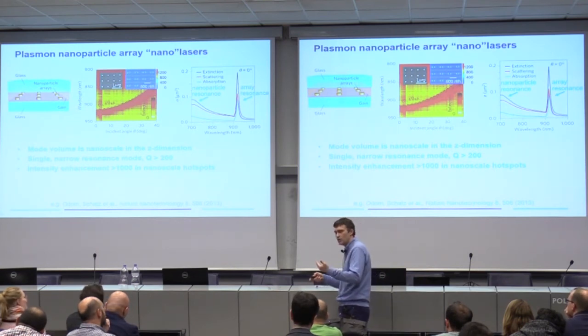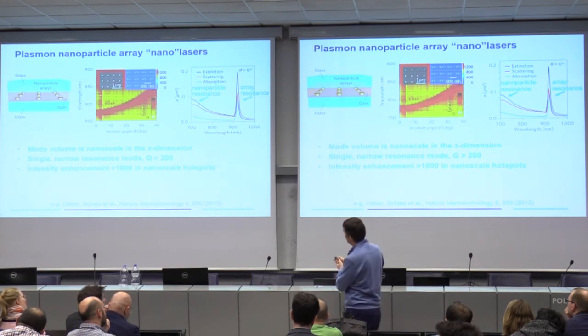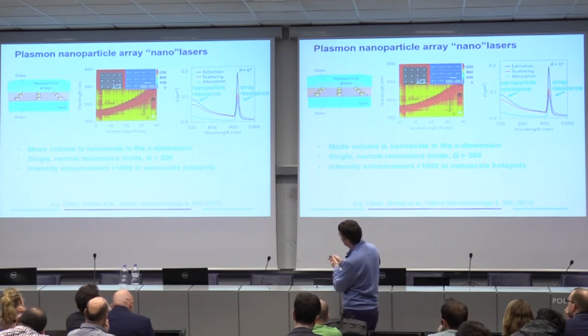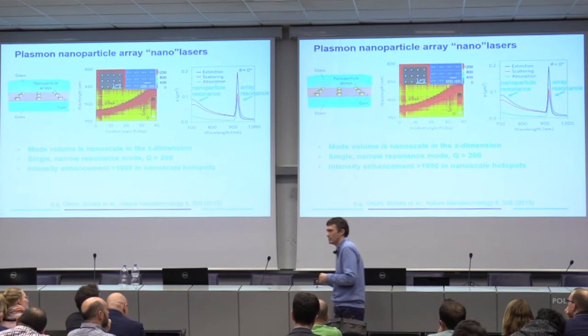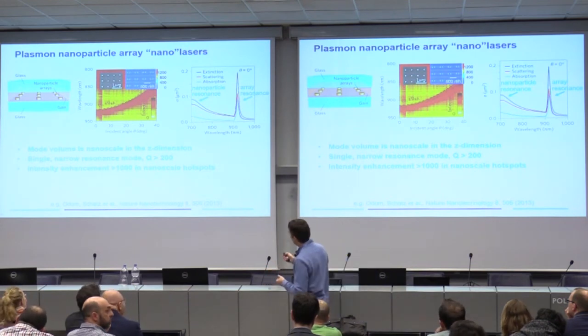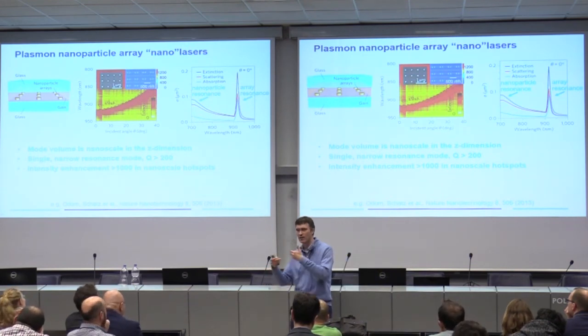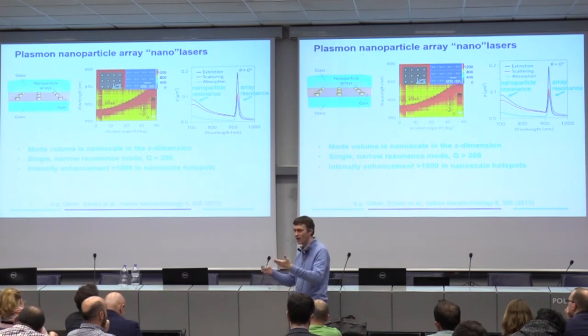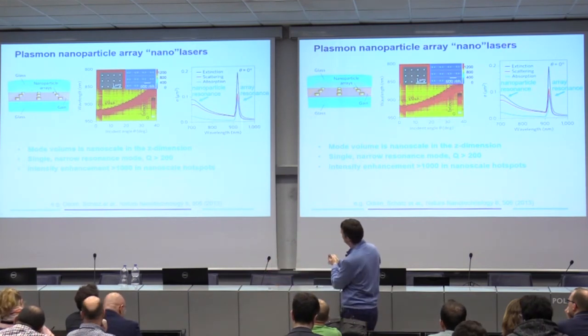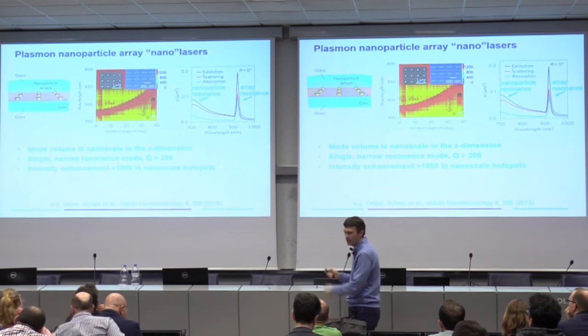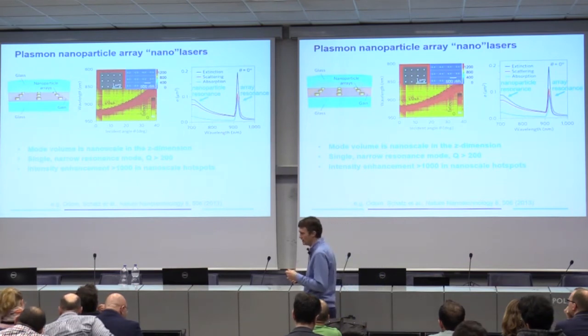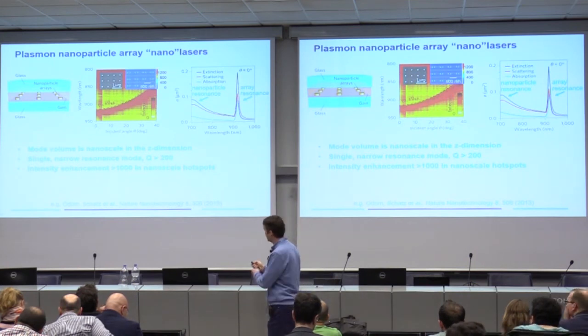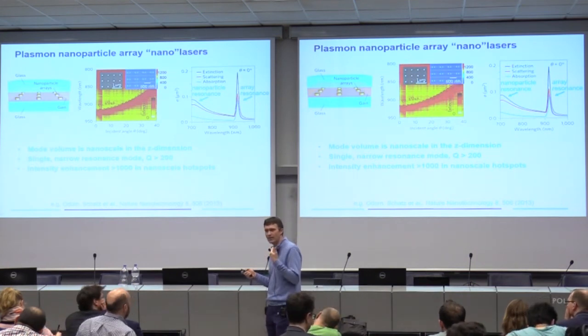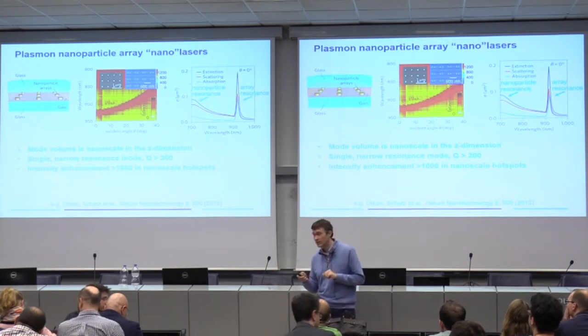And if you make a large array, what you get is not just, so every nanoparticle has a plasmon resonance, typically in the green to red region. And that's a broad resonance. But if you make an array such that you get this coherent scattering off of each particle, you can get a very sharp array resonance mode that has a relatively high quality factor, usually on the order of a few hundred, often up to about 1,000. And so we asked, can we use this mode to get lasing?